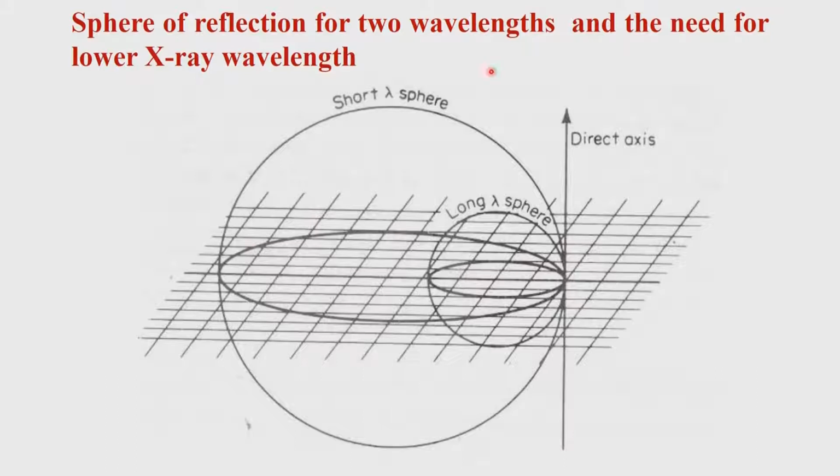So what we were looking at is to see now what is the wavelength which we can use, under what circumstances we can make sure that we get maximum number of measurements, because the whole logic of this X-ray structure determination depends upon how many independent reflections you can get in a diffraction experiment. This is the advantage of also the solid state and particularly the crystalline state, because it not only gives the possibilities of diffraction spots, it gives you an option of having a very large number of diffraction spots compared to what it is we have to determine.